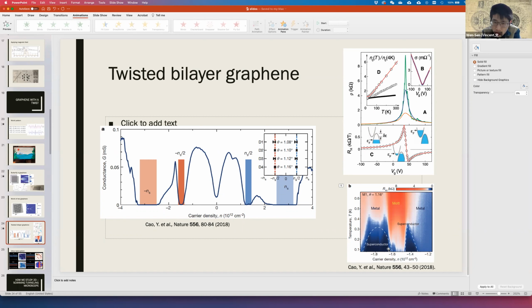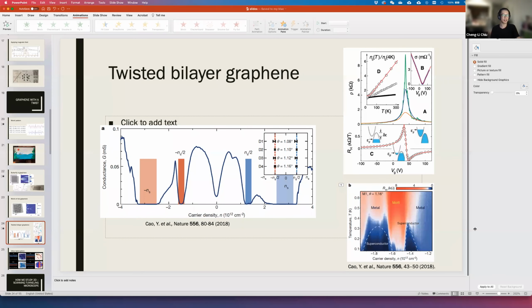And the bottom gate is sufficient to do that? Yeah. So the amazing part of this kind of material is that you usually get a large Moiré pattern, around 10 nanometer. So the 10 nanometer means that you can use that to calculate the carrier density, how much carrier density to fill one electron into a 10 nanometer by 10 nanometer Moiré cell. That's actually matching the capability of silicon oxide or boron nitride, that kind of material. So yeah, it happens to be sufficient, and yeah, very much a coincidence.